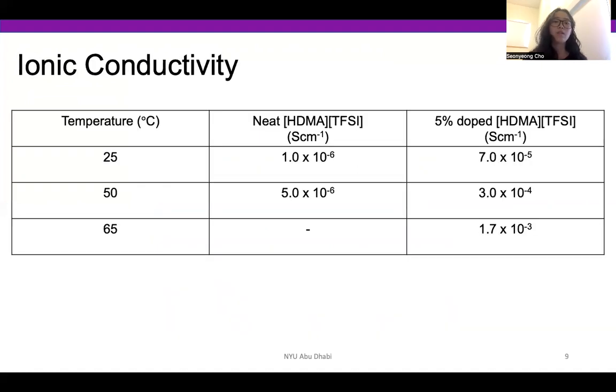And then the ionic conductivity of the material was measured. And the ionic conductivity is actually one of the most important parameters. So the ionic conductivity of the neat or the pure sample and the 5% dope sample is shown in this table here. And you can see a 5-fold increase in the pure sample after the phase transition temperature of 45 degrees Celsius. And this is due to the fact that the sample shifts from a more rigid phase to a